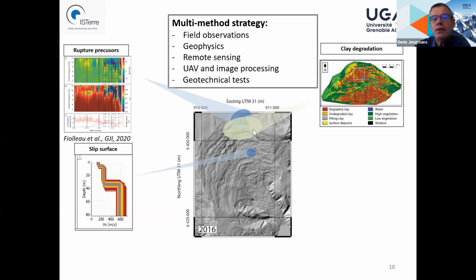In the upper part, where the blocks have slid inside the landslide, very quickly they are weathered, and so we tried to understand and study this degradation of the clay blocks. We studied this using UAV photos, classifying the material and computing the evolution of the surfaces of the different materials with time over a period of 2 years. And with the roughness, we were able to show a very high degradation rate of the clay materials in this zone.